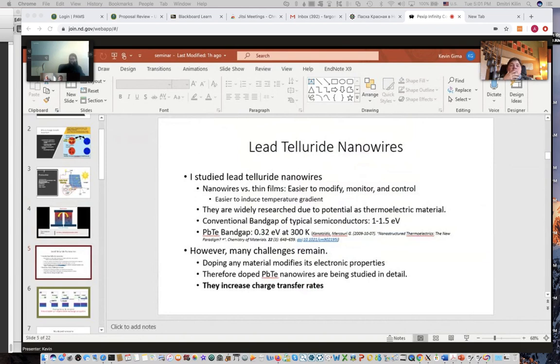So for instance, the conventional band gap of a typical semiconductor is between 1 and 1.5 electron volts. And researchers have found that the lead telluride band gap is 0.32 electron volts at 300 Kelvin. So that's really, really good compared to the conventional band gap I mentioned earlier. However, many challenges remain. Specifically, researchers are having some problems applying this technology to everyday appliances, and also in a regular unmodified lead telluride nanowire, the charge transfer is negligible.